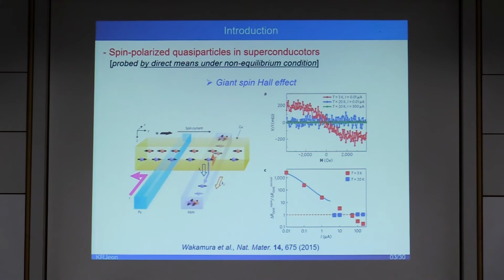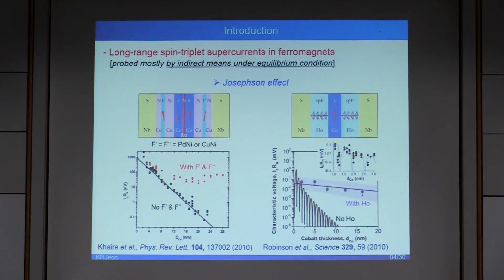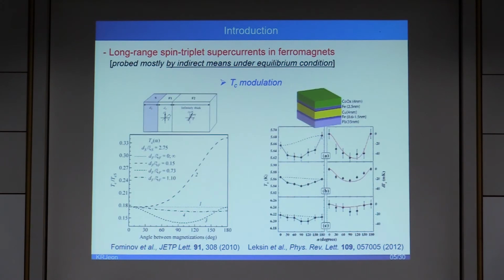On the other hand, equilibrium zero bias studies have focused on Josephson critical current in ferromagnetic Josephson junctions and critical temperature modulation in superconducting spin valves, which have demonstrated that static inhomogeneous magnetization configuration can generate long-range spin triplet pair correlation in the ferromagnet. Nevertheless, electrical observation of triplet spin transport through a singlet superconductor has not been demonstrated so far.